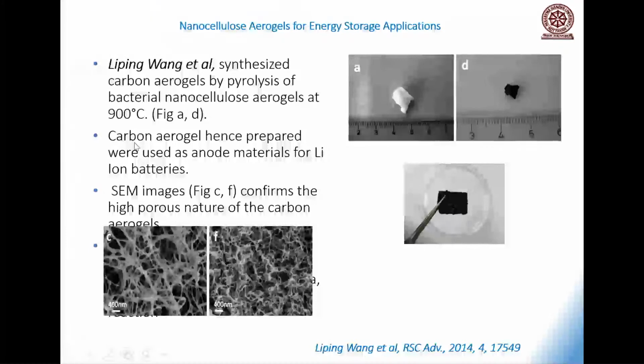And carbon aerogel, you know what he did? Carbon aerogel is extremely porous, and he found that this is a wonderful anode material for lithium-ion batteries. So you make nanocellulose aerogel, go for a pyrolysis, and you make beautiful porous carbon aerogel. This carbon aerogel is extremely porous, therefore electrolyte anode interaction is very strong. So this is very useful for battery applications.